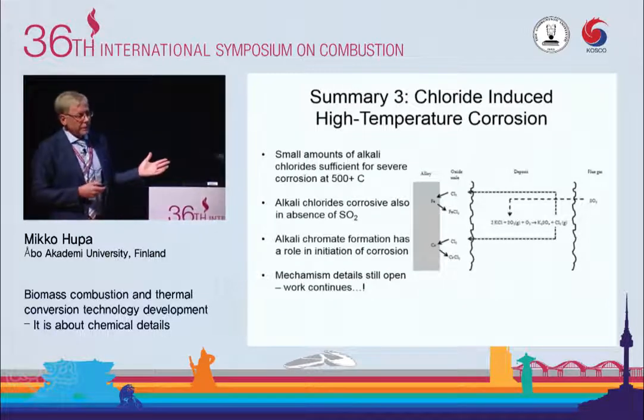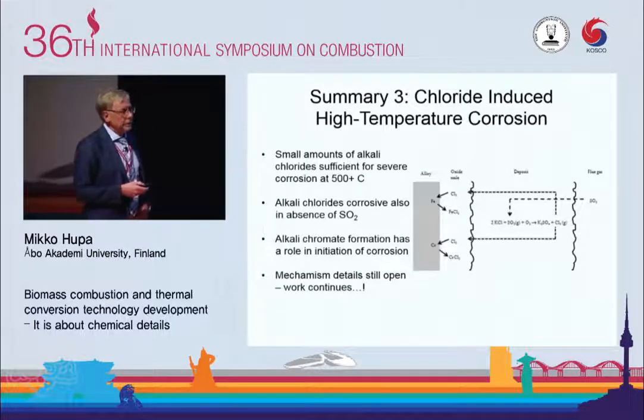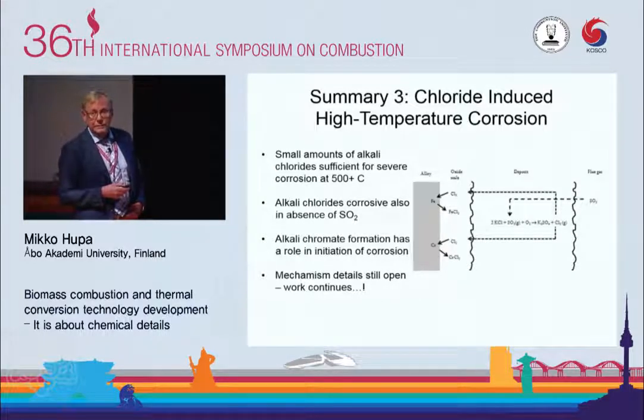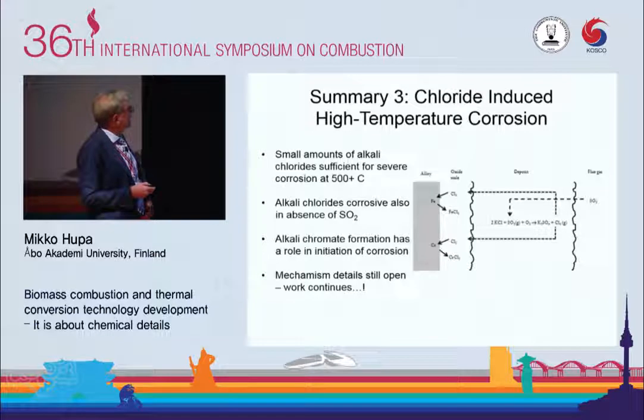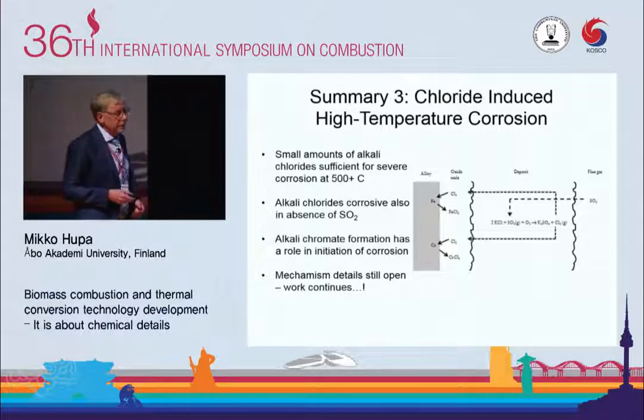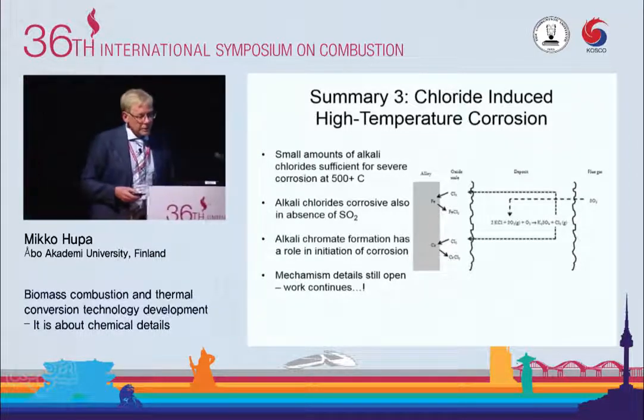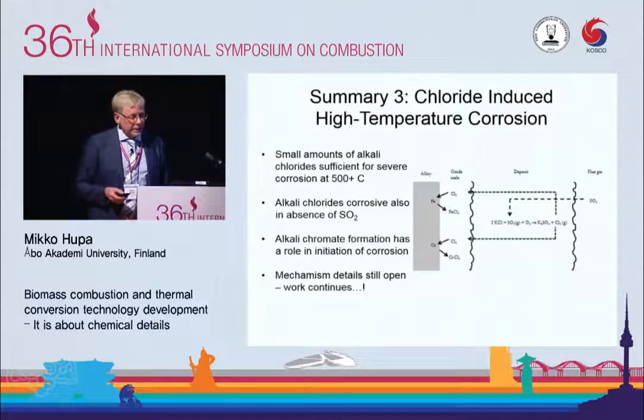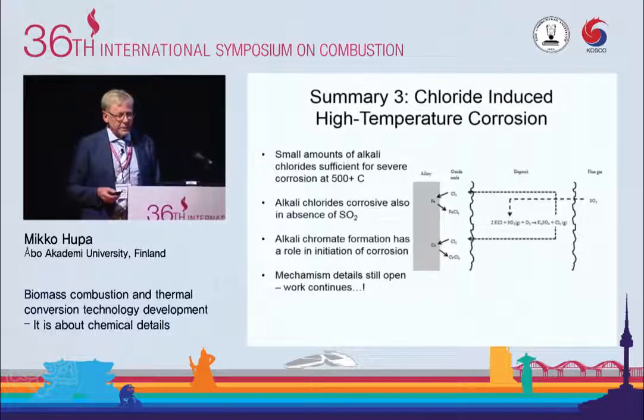Small amounts of alkali chlorides are sufficient for severe corrosion at 500 plus C. This is one conclusion. Alkali chlorides are corrosive also in absence of SO2. This alkali chromate formation has become an interesting thing. There is work going on. We try to understand a little better why, how that happens.